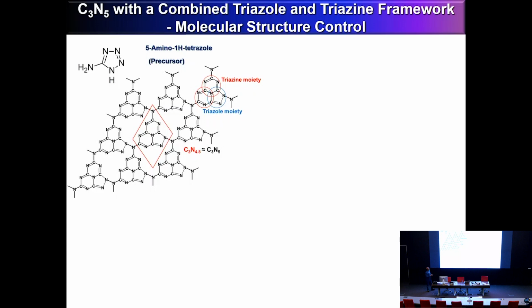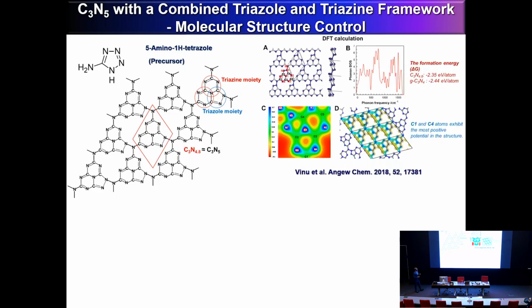We also checked the thermal stability of the material with density functional theory calculations. You see, the phonon density of states is quite positive. And also the formation energy of the carbon nitride C₃N₄ is almost similar to that of C₃N₅. So it is a quite stable material. What about the charge density profile? See, the C1 and C4 carbon atoms have the most positive potential, right? So that means you have an uneven distribution of the energy on the surface of this material.